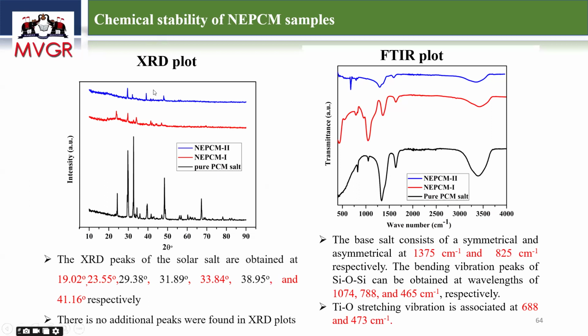This can be checked with the help of X-ray diffraction and FTIR, Fourier transform infrared spectroscopy. This is for checking the peaks. Most of the peaks will be available. The base PCM peaks will be available here, and the encapsulated PCM has the same peaks. Silicon peaks are also visible, and titanium peaks are also visible. All chemical compositions will be available. So it is confirmed that it is chemically stable.